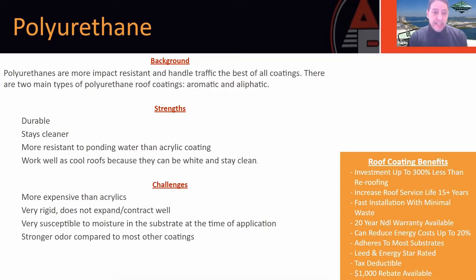Now, one of the main downsides of the urethanes is that it is very susceptible to humidity fluctuations. You have to be really careful what the conditions are when you're applying the urethanes, and also the humidity amount on the surface of the roof, the moisture that's in the roof or on the surface. Because this is where usually, when people have problems with the urethanes, it comes into play: there's humidity or moisture trapped when they coat down the urethanes, and then it tends to either blister or delaminate. So that's what you want to try to avoid when using the urethane coating system.